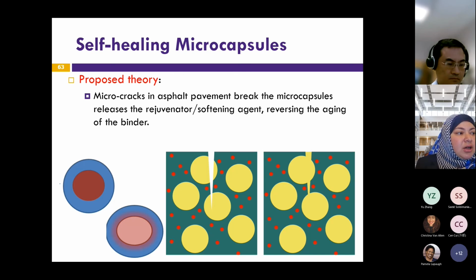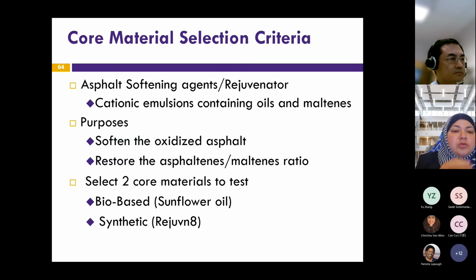We tried to implement that on the asphalt mix. So we created double-walled capsules that were made of urea formaldehyde and polyurethane. The healing agent inside is a rejuvenator, and we were looking for something to reverse the oxidation process or the aging of the binder by supplying oils and maltenes to the binder. So we tested two core materials: bio-based, which was just sunflower oil, the same oil that we use for cooking, and then another that is synthetic. It's called Rejuvn8 for the sake of the research.